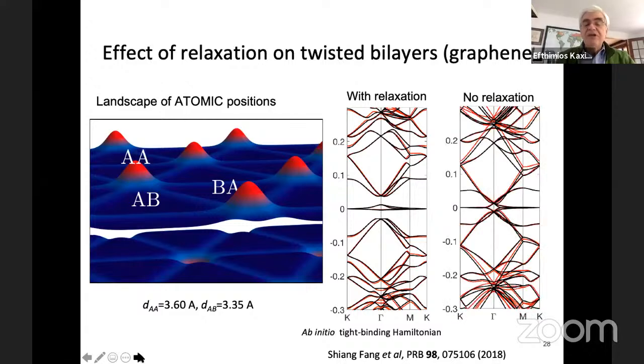So this is now a band structure. These are the different bands that correspond to this atomic arrangement. And you see these two bands here near the Fermi level at zero, and you see how flat these bands are. And flat bands give rise to very high density of states. If you did not include this relaxation, as was done earlier, before people could do these detailed calculations, you get this mess of electronic bands, which is not correct and not realistic. So the relaxation is very important.